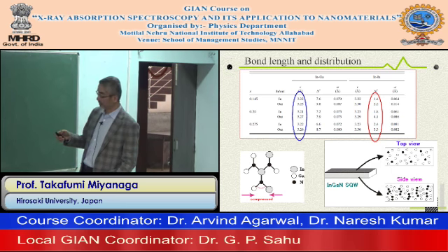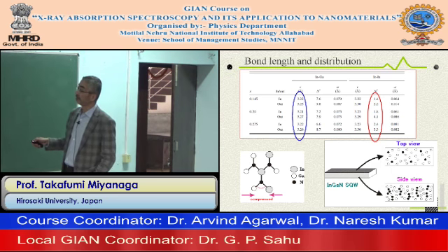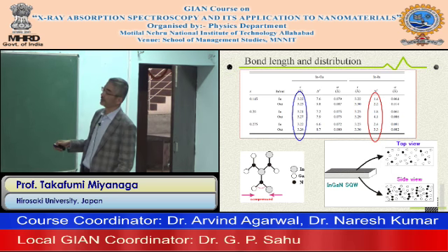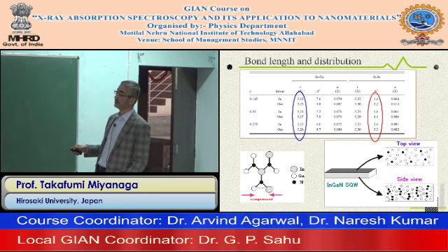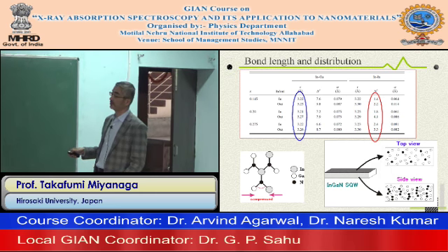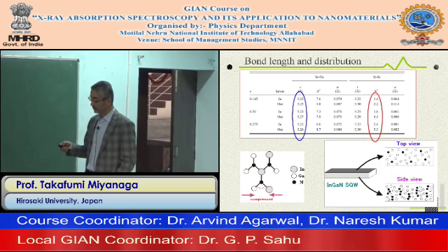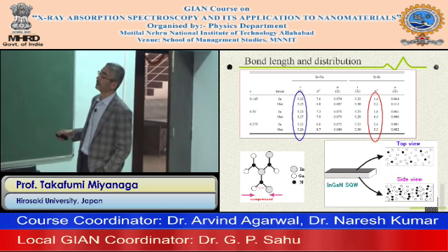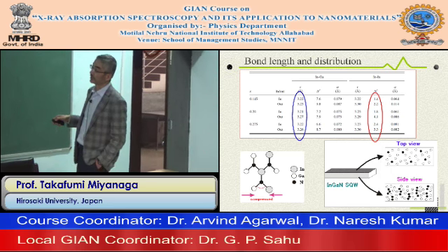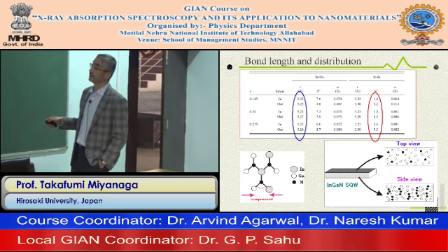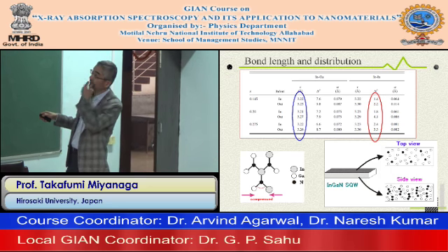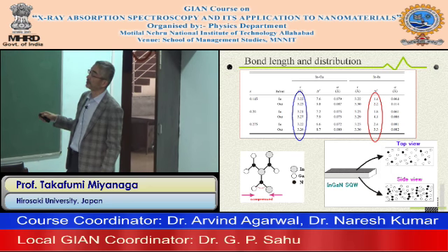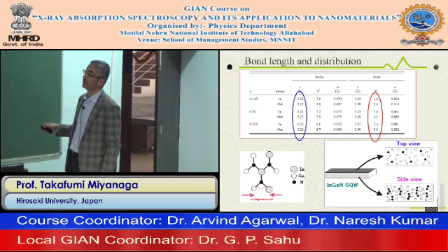Of course, the first peak is the same for the three types of colors, about 2.1 angstrom. After the curve fittings, for the second peak we concentrated the discussion on indium-gallium and indium-indium, the second nearest neighbor peak.